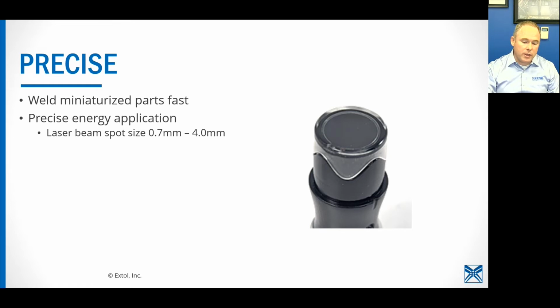This part is smaller than a dime, and we're able to weld that in about 1.5 seconds with only 25 watts. I'll talk about wattage in just a moment. You can get really precise energy application, 0.7 millimeters, all the way up to 4 millimeters if you need it. What's more typical for us is around 1 to 2 millimeters.